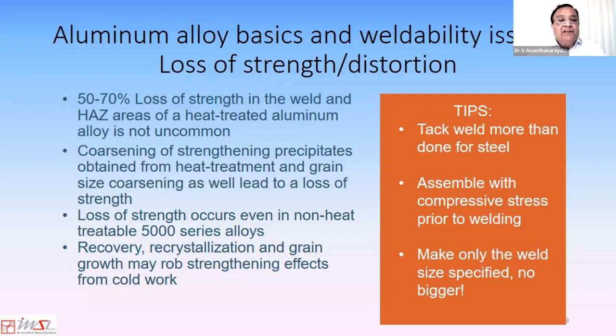And the loss of strength occurs even in non-heat treatable 5000 series alloys, as I mentioned. So the recovery, recrystallization, and grain growth rob strengthening effects from cold work as well. And what can one do here? One can tack weld more to help with the distortions and assemble compressive stress if possible, so that the residual stresses are not so adversely affecting the application, and only make welds that are as big as needed, no bigger. If there's a thought process that larger welds can hold more load, that is a completely wrong idea with respect to aluminum.